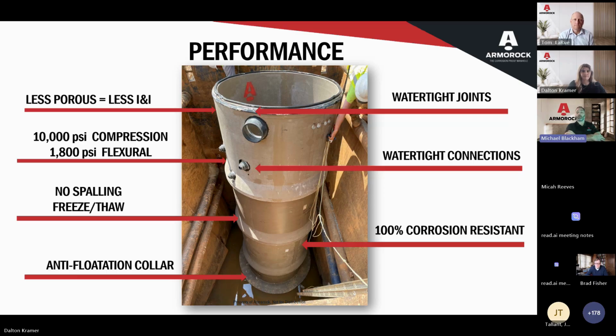We also have watertight pipe connections, similar to what you're used to seeing with boots. And when required, we offer engineered anti-flotation collars that are designed to address any buoyancy risk issues that you might have on site. Last but not least, most importantly, Armorock polymer concrete is 100% corrosion resistant. It's not a liner, it's not a coating or a surface treatment, but because the corrosion resistant properties of all the materials we use exist throughout the entire structure, it becomes 100% corrosion proof. So this is key for sewer applications. This is what's going to provide that long-term durability that we should be looking for in our sewer environments.